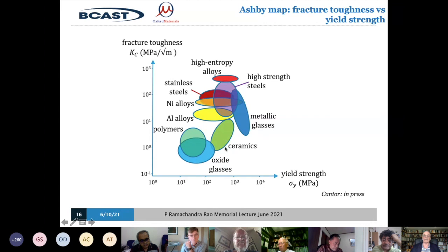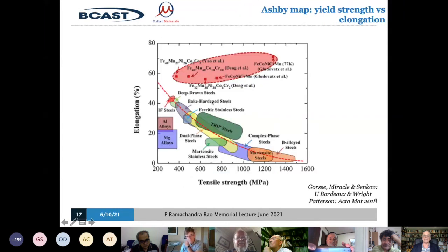And in fact, if we do this plot here, this is slightly more up to date, then these are all the different steels, and these are the FCC Cantor alloys. And you can see now a lot of the different compositions. You can have different components, you have different percentages of each of them, and still be in the single phase, face-centered cubic region where you have this particular set of special properties. And this is the formability, the amount that you can stretch the material, and this is the strength. So you can see they're well above all the very best steels.